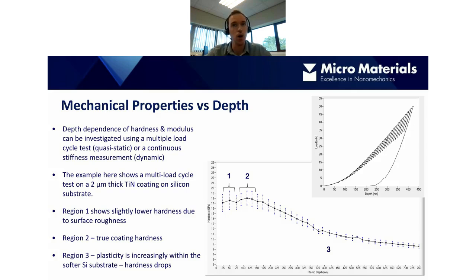This is what we call a multiple load cycle test, whereby we perform an indentation with these increasing load steps. So the load increases, and then we have a partial unload period, and then the load increases onto the next step. So this is a single indent in one position on the sample, but with these multiple unload steps. And we can use the standard Oliver and Pharr analysis to get a value for hardness or modulus for each of these unloading steps, and then we can plot that as a function of depth into the sample.